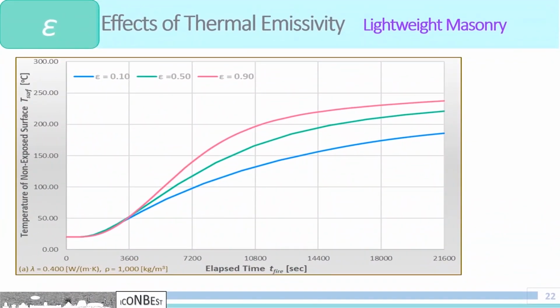As shown in this graph, an increase of the thermal emissivity leads to a parallel increase of the resultant temperature of the non-exposed surface. Thus, for lightweight masonry walls subjected to fire, the maximum surface temperatures are as follows. For an emissivity equal to 0.1, the maximum temperature reaches a value equal to 185 degrees. For an emissivity equal to 0.5, the maximum temperature is 220 degrees, while for an emissivity 0.9, the temperature is 235 degrees. It is worth noting that as the value of the thermal emissivity rises, its effect on the temperature values weakens. Moreover, the rate of temperature increase declines as it asymptotically approaches a constant value.